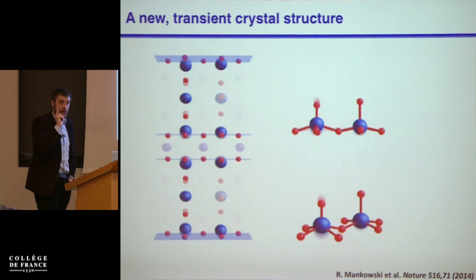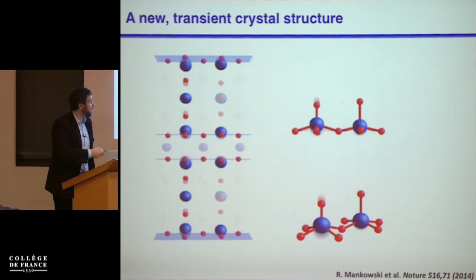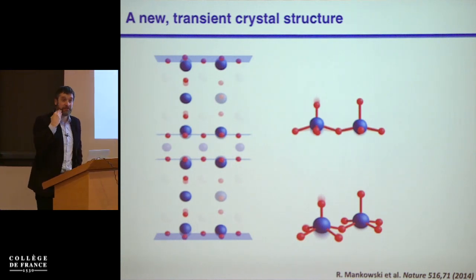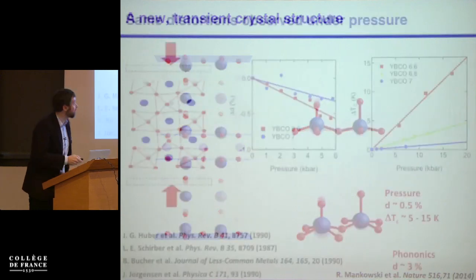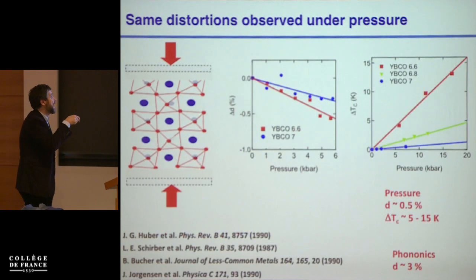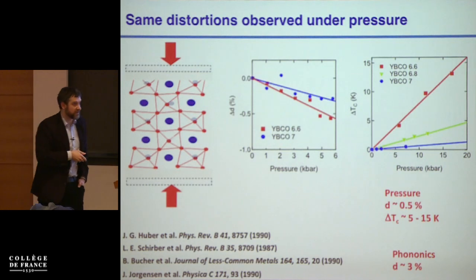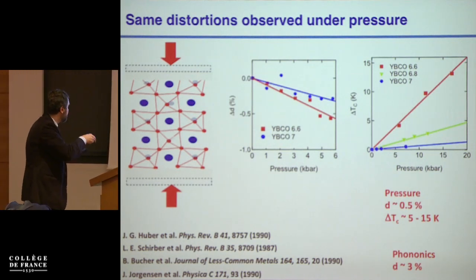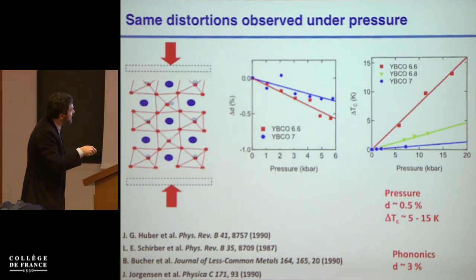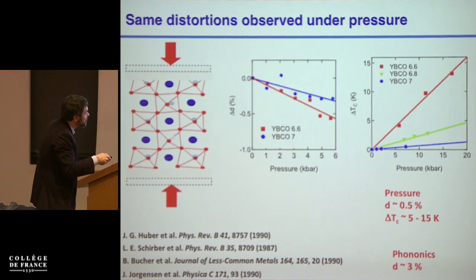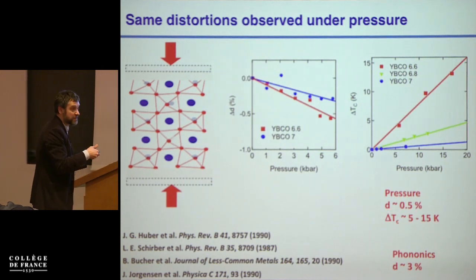One important thing that I want to point out, actually, is that these changes are very similar to the ones that you observe statically when you apply static pressure. There's a number of experiments that have been done statically. This is where people have measured, for example, pressures up to a degree where the crystal would crack. And they would have observed, for example, motions of the apical oxygen by about 0.5%